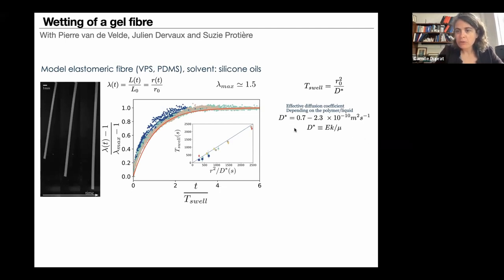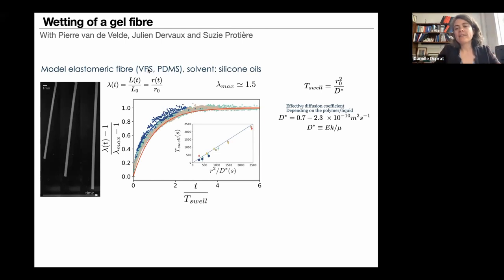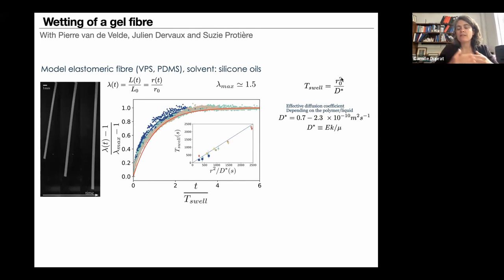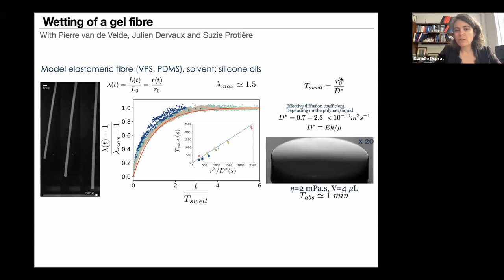With our system we have typical diffusion coefficients of 10^-10 m²/s. We can only slightly vary this coefficient because changing the elastomer chain length simultaneously decreases the Young's modulus and increases the permeability, keeping D_eff roughly constant. The swelling timescale is mostly dependent on geometry — the size of the fiber — giving absorption times of a few minutes. For example, placing a 4-microliter droplet on a flat block of this polymer, it will spread and be absorbed in about one minute.